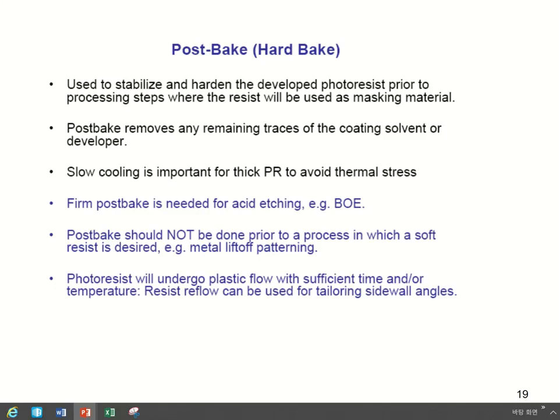In this post bake process, you want to make sure your pattern, the PR, is stable, to withstand the etching process and any other process after this. So you stabilize and harden the developed photoresist prior to the processing steps where the resist will be used as a masking material. Post-bake also removes any remaining traces of solvent or developer. Also, after the hard baking, the patterned PR structure will be used for coating or etching, to protect the substrate.